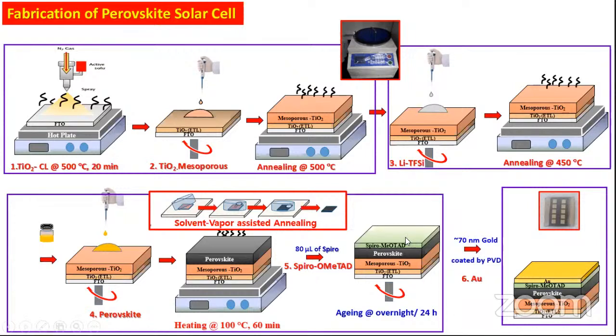Then after that, we coated the hole transport layer, Spiro-OMeTAD. Then finally, the gold counter electrode was coated. This is the solar cell device. The active area of the cell is 25 mm square.